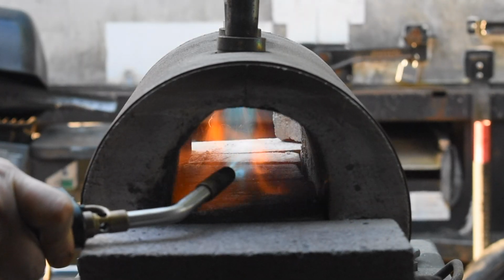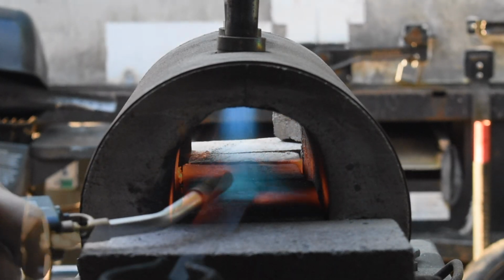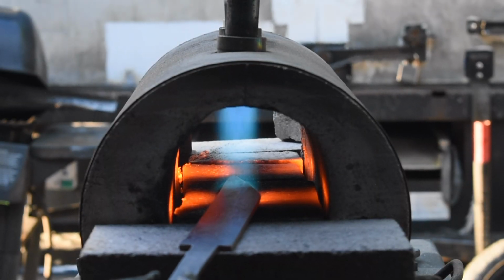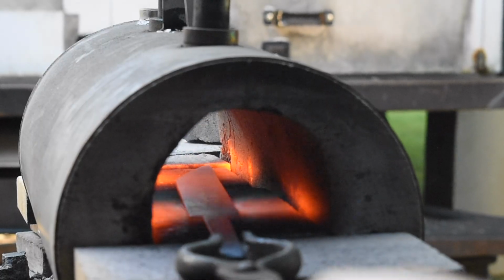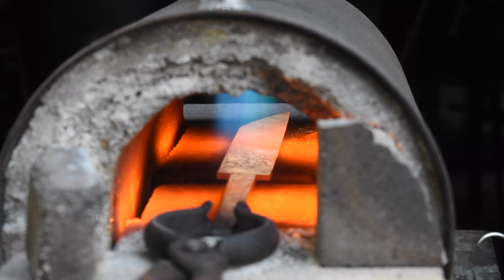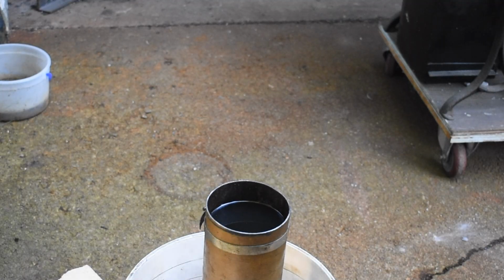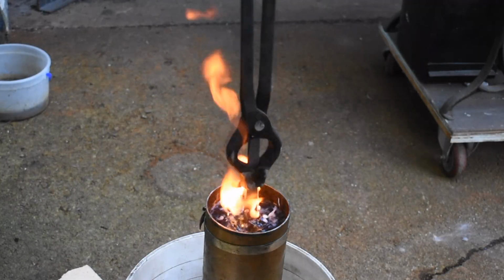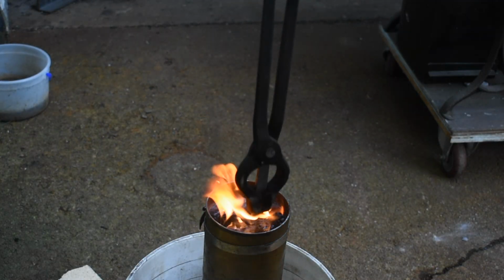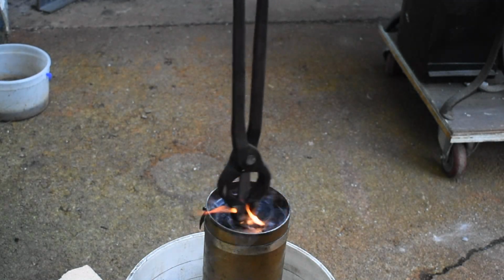And now I'm ready to quench the blade. I'll heat the blade up to 1550 degrees, and I'll try to make sure I get as even a heat as I can before I go for the quench. And then I'll quench the blade in the Parks 50 quench oil, and I make sure to preheat the quench oil to 120 degrees.